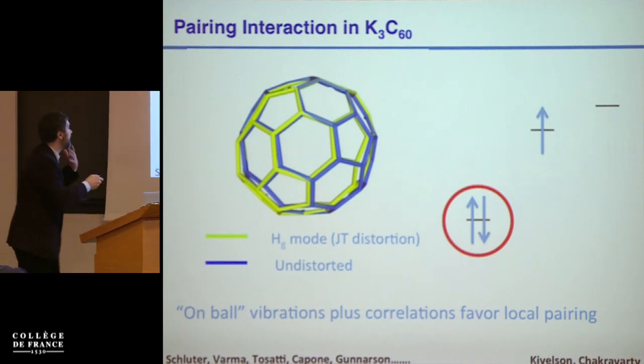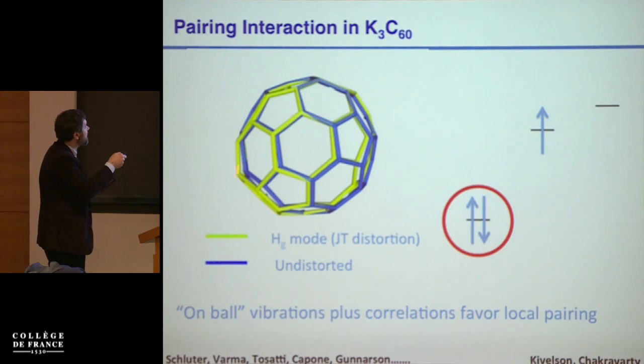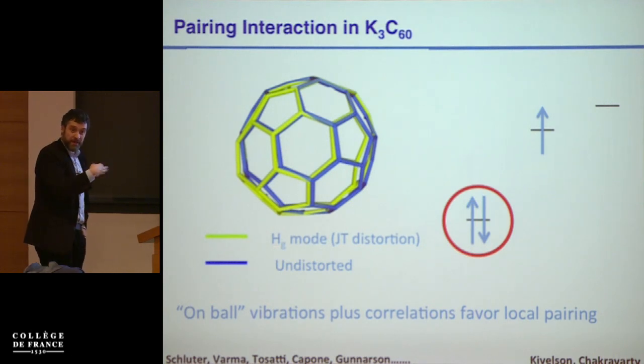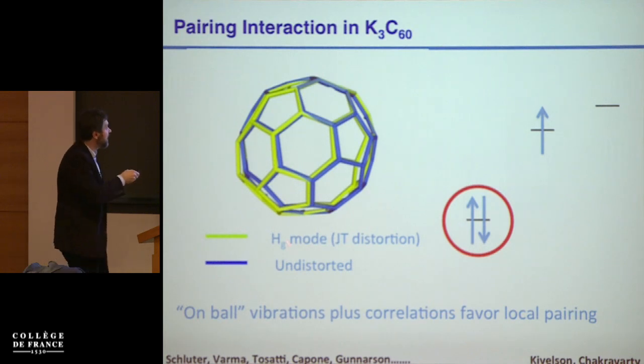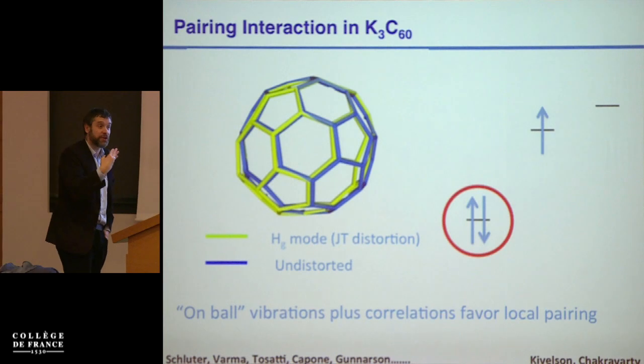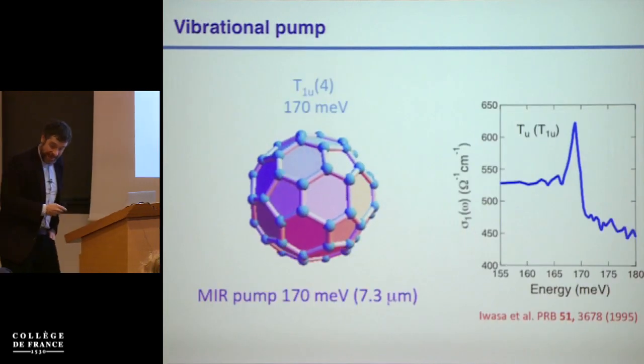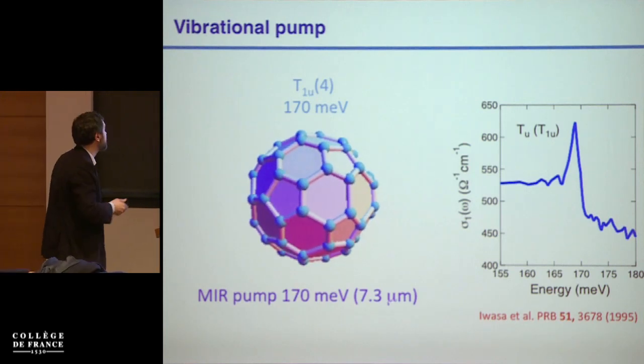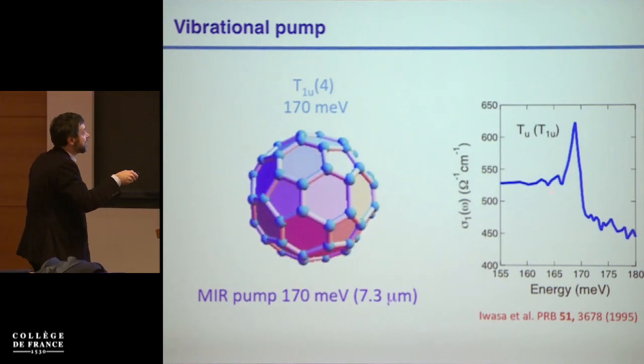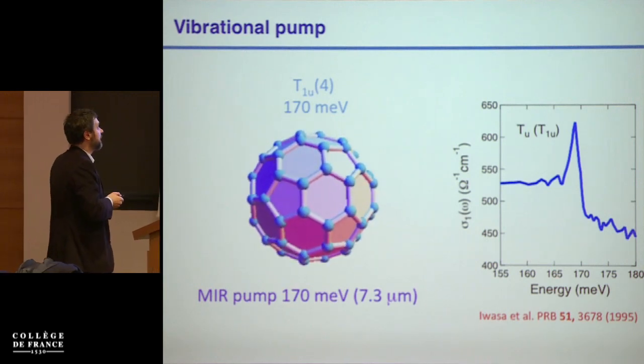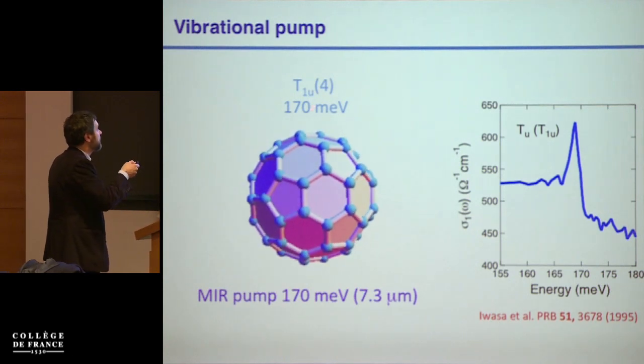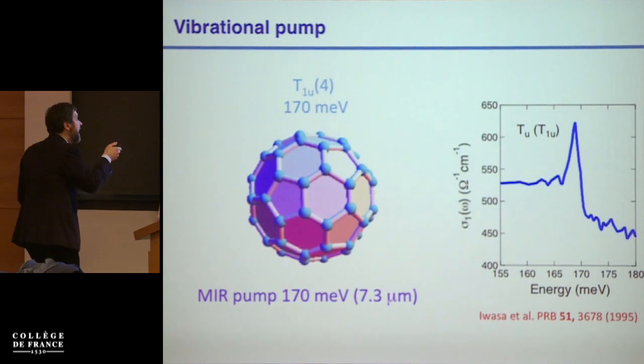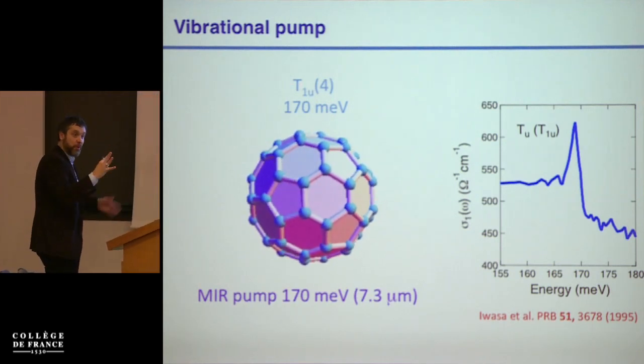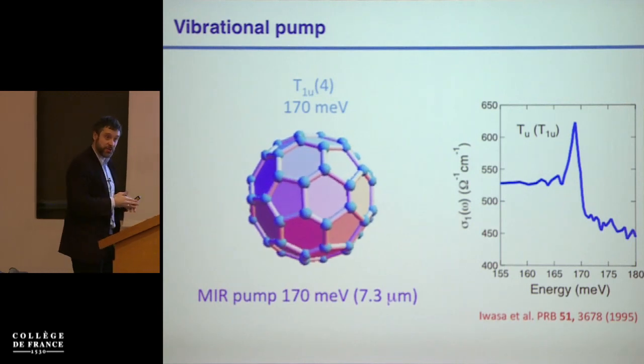So what we started thinking about was to drive these vibrations, or something that was related to this mode that was known to help superconductivity, and try to activate this by nonlinear phononics and see if we could increase Tc. So what we did here, which will probably not be exactly what the mechanism is, we excite this T1u mode, which is observed clearly only in the single crystals, whereas it kind of disappears into the polaronic peak that I showed you before in the powders. Excite this mode to large amplitudes at about 7 microns, and then rely on the coupling between this mode and the H modes to perhaps deform the lattice along the direction that is good for superconductivity.